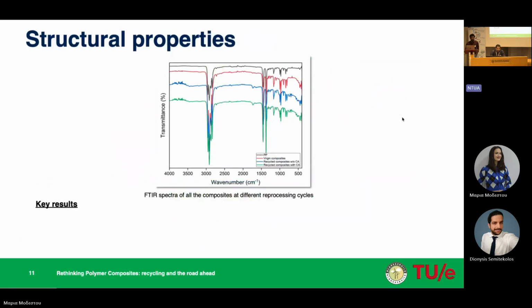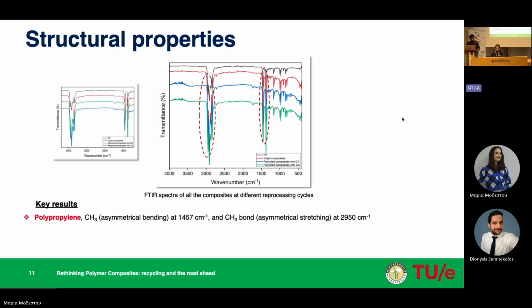So after reprocessing the secondary composites and producing these specimens from injection molding, we also analyzed structural properties of these composites. As we all know, since these composites undergo multiple reprocessing cycles, there is a possibility for these composites to lose their structural properties, right? So in order to assess these structural properties, we did FTIR in order to assess the effect of reprocessing. As you can see here, the corresponding peaks for polypropylene were not altered, which means the polymer matrix was not entirely altered even after reprocessing for 3 cycles.